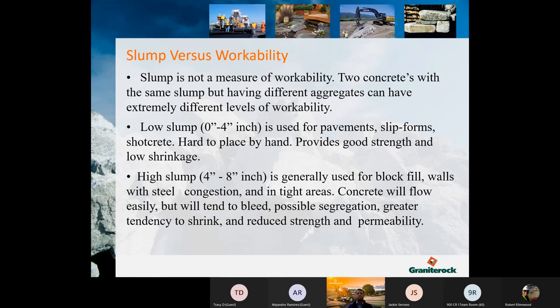Higher slumps are generally used for applications such as block fill, walls, other areas with steel congestion, and other tight areas. Concrete will flow easily, but it does have a tendency to bleed more, water rising, there is a possibility for segregation, and it does have a greater tendency to shrink. And all this reduces strength and permeability. The main reason for that is usually higher water contents.